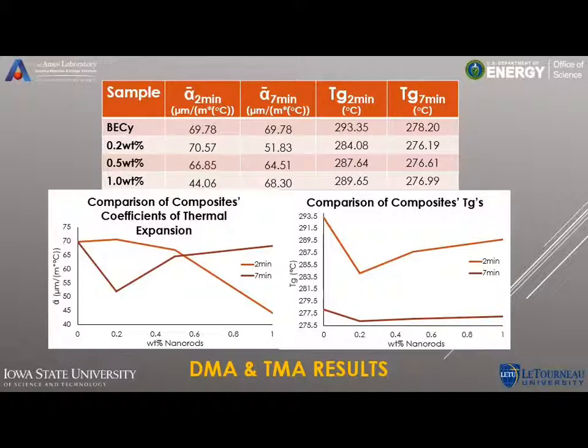On the left-hand side, you see the measurements with the TMA for the coefficient of thermal expansion, and that showed the greatest drop in the coefficient of thermal expansion for the 0.2 weight percent. Again, the first 2-minute set had that deviating sample in there, so it's less reliable data. And then on the right-hand side, you can see the DMA measurements, or the dynamic mechanical analysis, and those measured the glass transition temperature. And there, again, you're seeing that the 0.2 weight percent is showing the greatest drop in glass transition temperature.